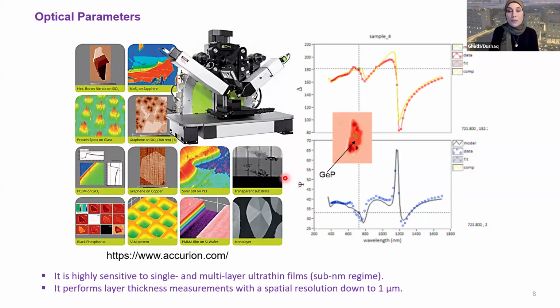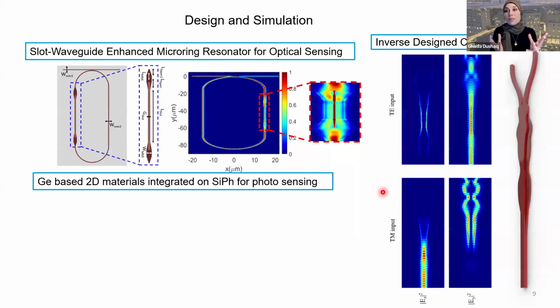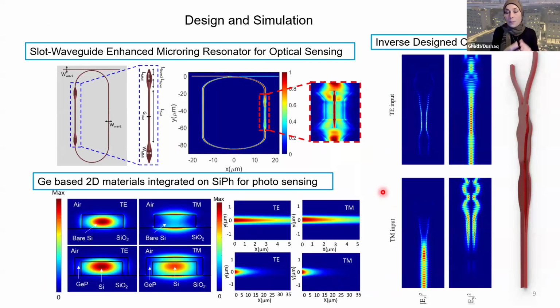We've been lucky to have this system from Accurion with which we managed to extract the optical parameters based on the complex refraction coefficient, then do fitting by knowing some simple physics about the material, semiconducting or metallic, to know the model that we could fit to it. So we managed to get the optical properties of different exotic materials. Knowing these optical properties allows us to design our problem in a very good way by feeding these optical parameters to a simulation kit like Lumerical. So you can do slot waveguides, you can do silicon nitride, you can understand the effective index of refraction distribution and understand the light-matter interaction, depending on what you want to do in terms of application.